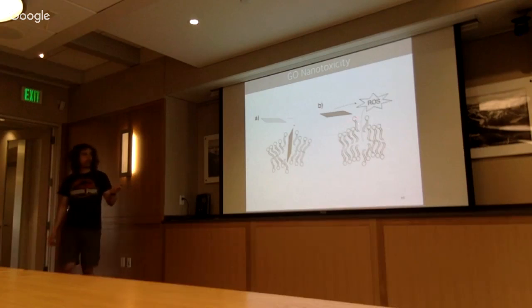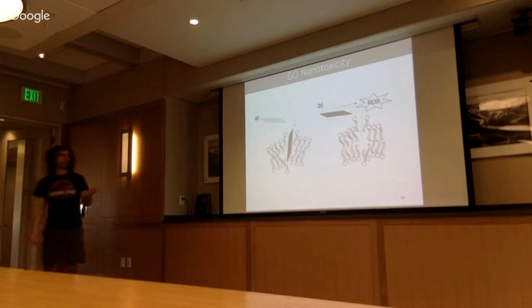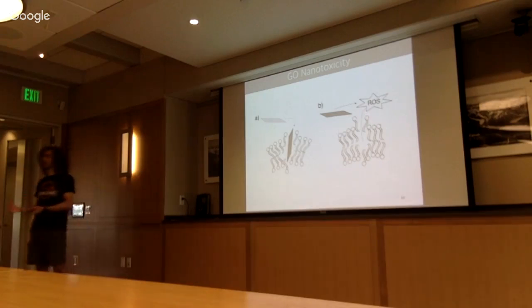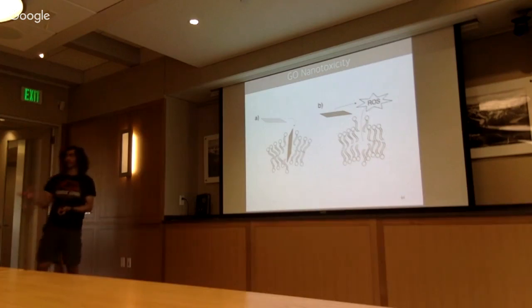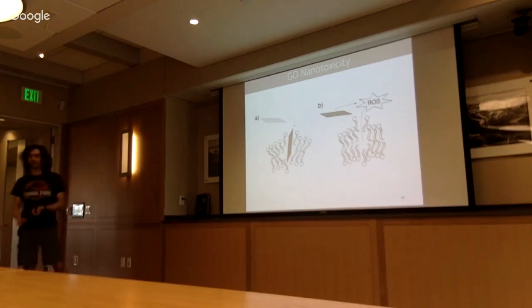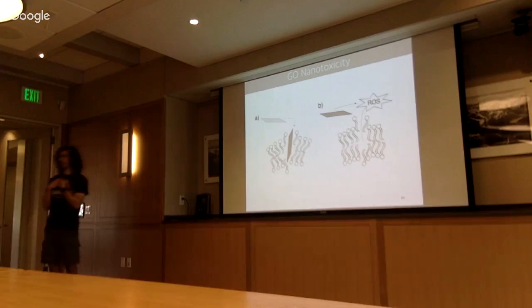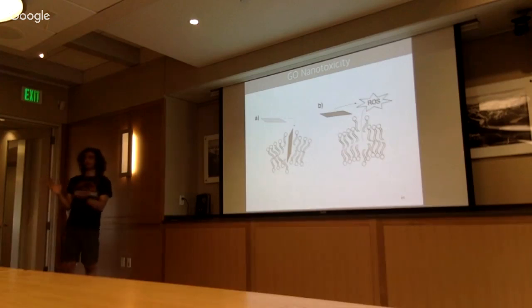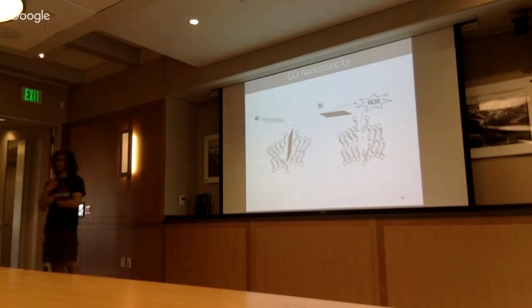The other mechanism basically says that graphene oxide might be involved in the production of reactive oxygen species that can alter the cell wall, or even worse, they can alter the metabolic function of the cell. So in our case, we're making this membrane for water treatment, right? So the main exposure path will be like ingestion.